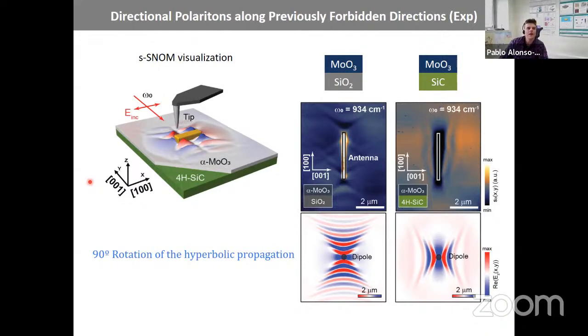Yes, we think so. Here we just did it with silicon carbide because it was the obvious choice: get the silicon carbide substrate, put the flake of MoO3 and do the experiment. But we can, for example, use a silicon dioxide substrate with MoO3, and then put another substrate with a negative permittivity, where the condition that the real part of one plus the real part of the other is negative holds. Then we expect the rotation as well. We have one demonstration that proves it, and we think it will work also for others. This is the great thing about van der Waals materials and all this twisting.